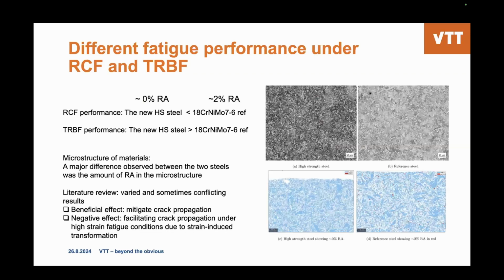We have investigated microstructure. Here, the optical image shows very similar martensitic microstructure for both. But the major difference we found is in the retained austenite. The high-strength steel has a nearly 0% retained austenite level. And for the reference steel, we can see some very little points. This is analyzed by MTEX, the phase analysis. Those are the retained austenite phase.